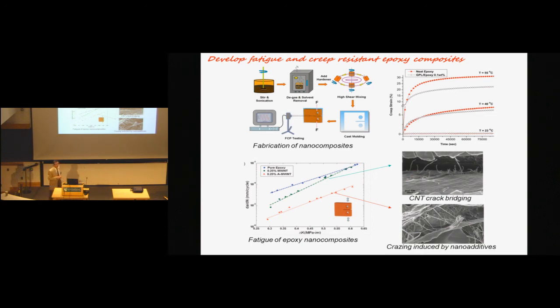Okay? Now, what happens is something surprising, in fact. You can put a crack in this material, and you propagate the crack. You stop the test before the specimen fails, and you look very close to the crack tip. In the first material, when we use carbon nanotubes without functionalization, what you observe is that the tubes are just sticking out from the crack surface. What you see here is the lower crack face, this is the upper crack face, and you see these carbon nanotubes sort of trying to bridge the two faces of the crack. They give some toughness, of course, because of crack bridging, because they link the two faces of the crack, but not that much.